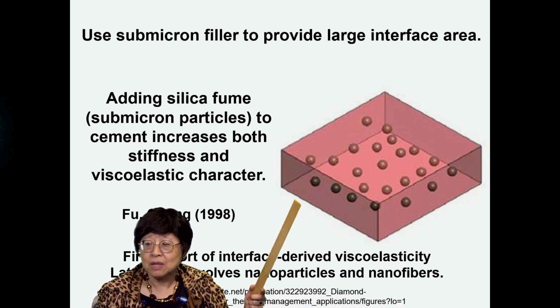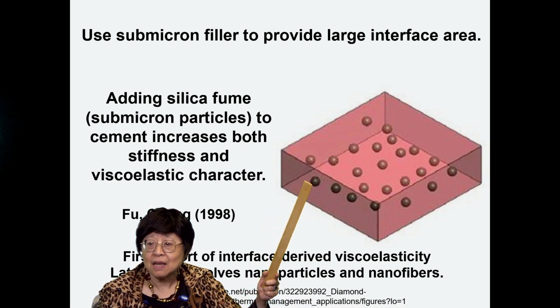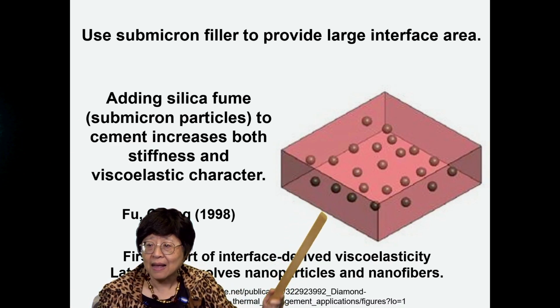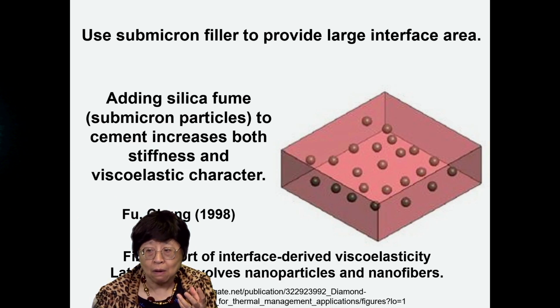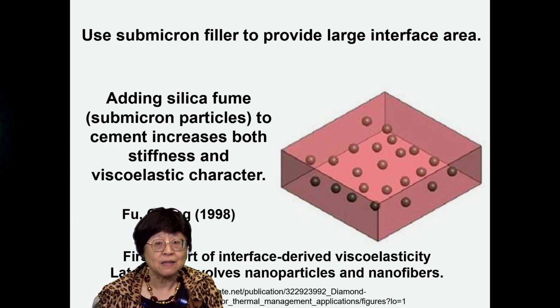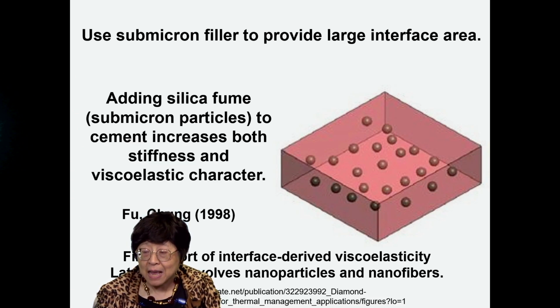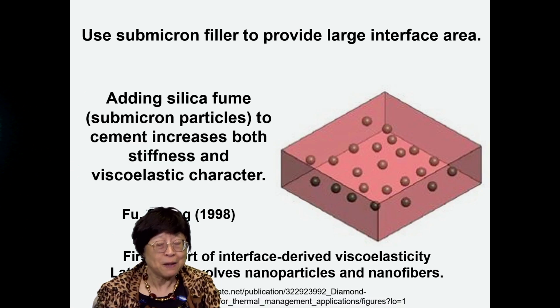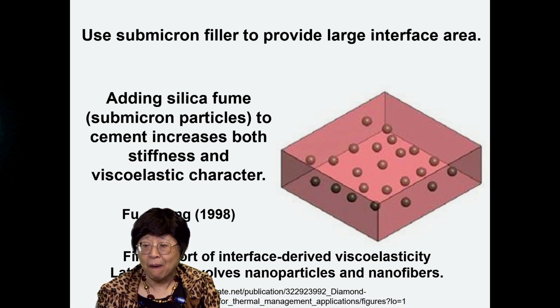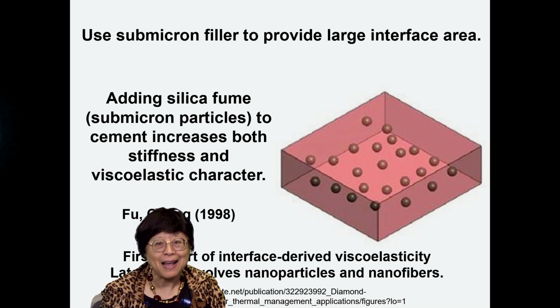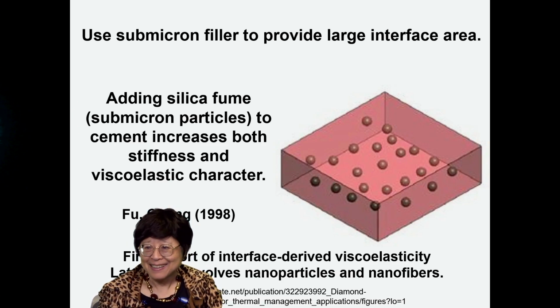In this first example, we used a cement matrix and put some silica nanoparticles into it. Because the particle size is so small, you have a lot of interface area, and therefore it becomes more able to dampen. At the same time, these particles are reinforcement, and they strengthen the material. So adding these particles improves the stiffness and the viscoelastic character at the same time. That was like magic at the time. People couldn't believe me, but now they do.